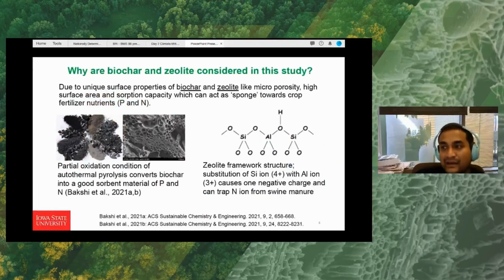So why are biochar and zeolite considered in this study? Both biochar and zeolite have unique surface properties. They have high porosity, microporosity, high surface area, and high absorption capacity, and they can both act as a sponge towards crop nutrients like nitrogen and phosphorus. On the left side, there are some pictures of the biochar and scanning electron microscopy pictures of the biochar, and on the right side, there are pictures of the zeolite framework structure.